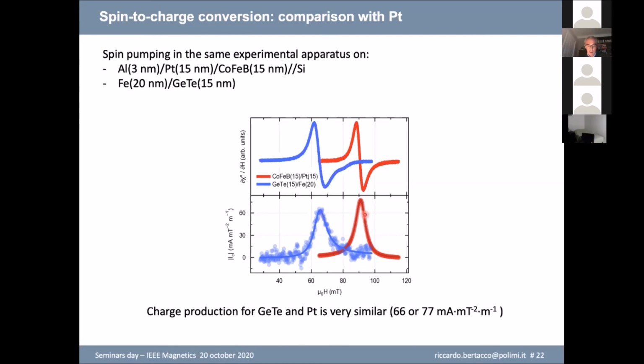So that's good news, because it means that in principle we can now work on germanium telluride like in the case of platinum, for instance, for producing spin orbit torque in some materials, having in mind that in germanium telluride we can also have this additional degree of freedom, which is the possibility to store a variable state written in the ferroelectric state.